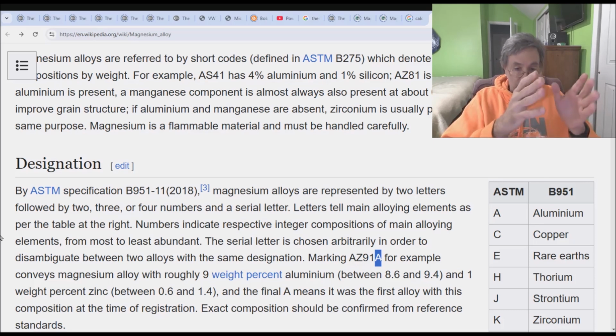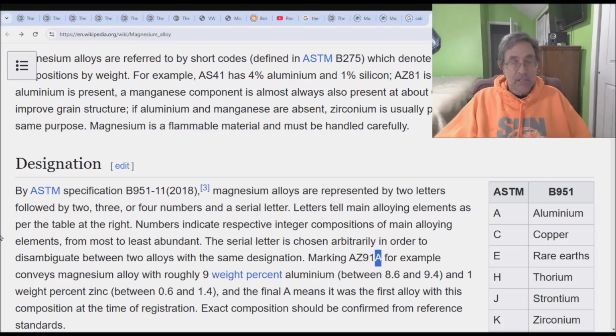Still has to have the 4% aluminum, the 1% silicon. And then you vary the other pieces by a little tiny bit. We'll call them constituents or components. You can vary not really the strength, but you get things like machinability. You get subtle tweaks to heat transfer, and I think one of the ones that they do is manganese, and I think the manganese is put in there for corrosion resistance. But we need to now venture off of the AS41 designation because we now know what they mean, that it's not an arbitrary Volkswagen designation, it is an ASTM specification that defines what the alloys are.